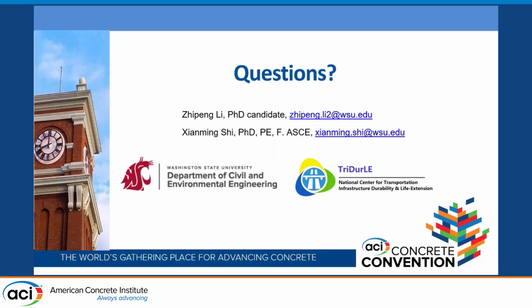Yes, thank you. From the Swedish experience, we know that composites and other paintings do not work because they prevent the concrete from breathing, and then the moisture inside will cause damage. We know that traditional impregnation using silane and silicate works very well, at least for 15 years. But your material also seems to work well. Is it that much better than traditional impregnation? Is it cheaper, or have you made a comparison between silane and silicate and your material?